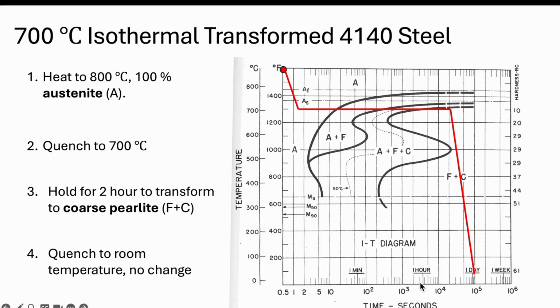So I do want to make one kind of quick note here, is that let's say we have a furnace that we're doing this experiment with, and there's a little difference in the temperature. So let's say we maybe, instead of at 700, we're actually up at like 725 or 750, closer up here that you see here. So when that happens, something interesting can happen, right? So essentially we don't catch this reaction that we're seeing with the dark lines. We just form maybe ferrite, but we still have austenite.